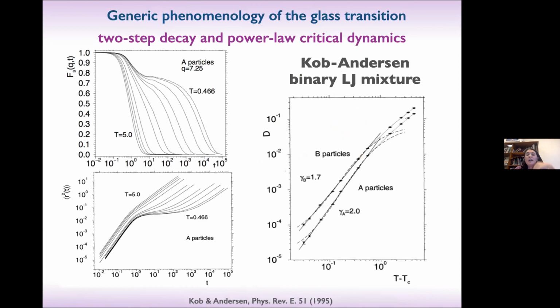So I just want to finish this introductory part saying that this two-step decay is a generic phenomenology of the glass transition. And this is the famous article by Walter Kob and Andersen about a binary mixture Lennard-Jones, a binary mixture because otherwise, if you take just the monodisperse, the one-component Lennard-Jones, it will crystallize. You see that the behavior in temperature, now that is the relevant control parameter, at a fixed packing fraction, is you have this onset of two-step decay in the density relaxation, self and collective.